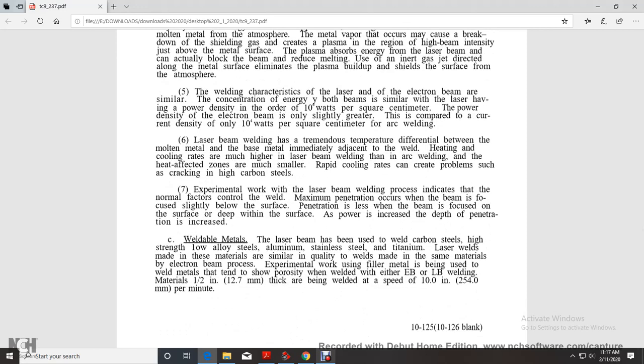The welding characteristics of the laser beam are similar to the electron beam, with concentration of energy in both beams, and the laser having a power density on the order of 10 to the sixth watts per square centimeter, with the power density of the electron beam only slightly greater. In comparison, the current density of arc welding is only 10 to the fourth watts per square centimeter. The laser beam produces a tremendous temperature differential between the weld and the base metal immediately adjacent to it. Heating and cooling rates are much higher with laser beam welding. Compared to arc welding, the heat affected zone is much smaller. Rapid cooling rates can create problems such as cracking in high carbon steels.